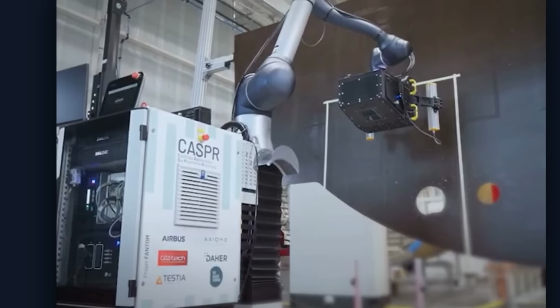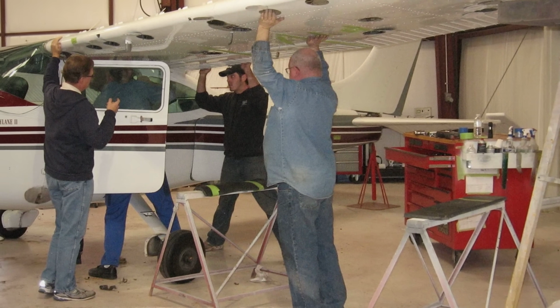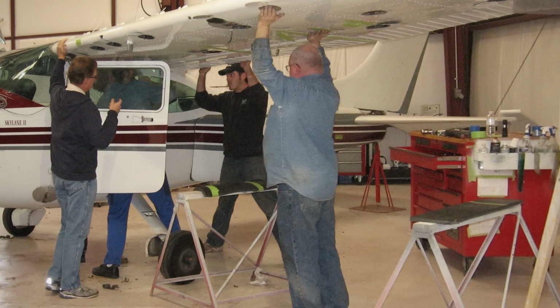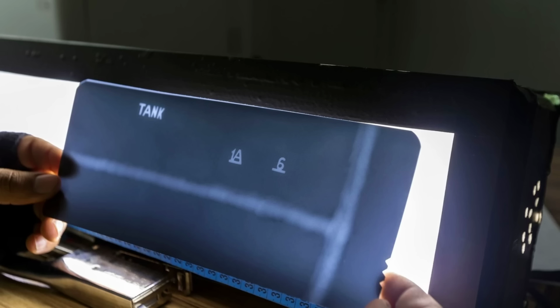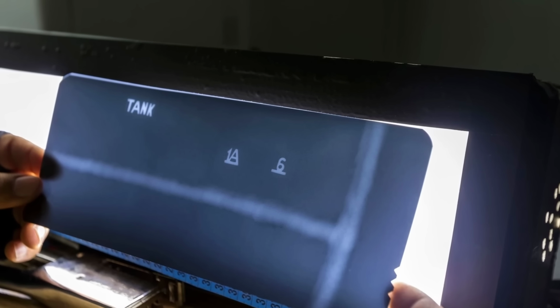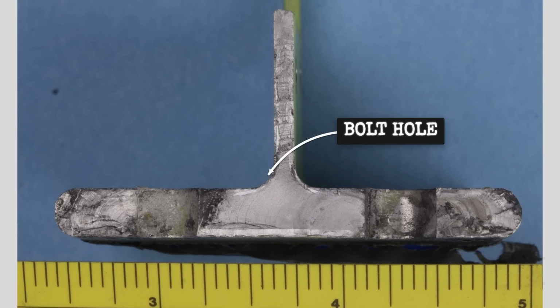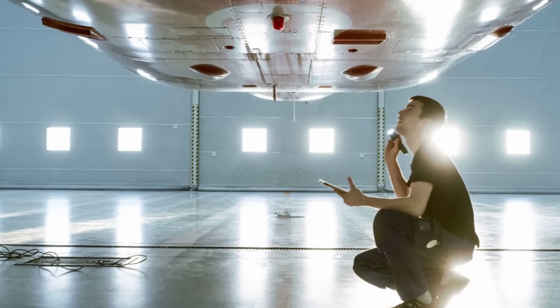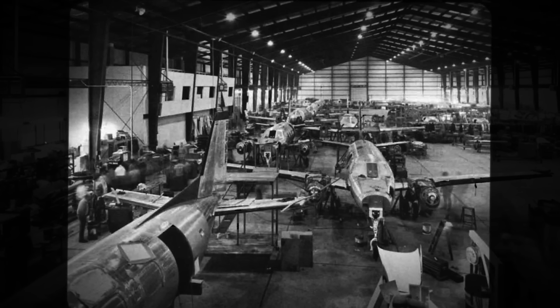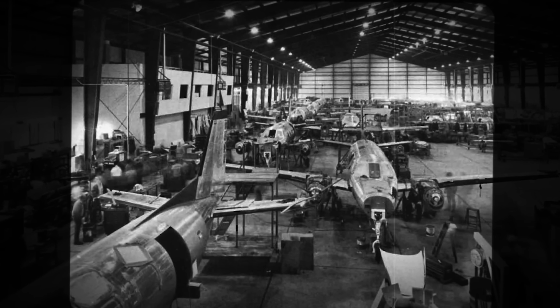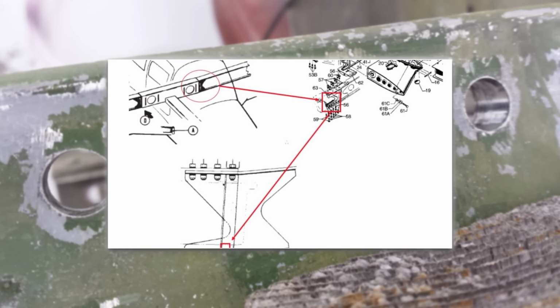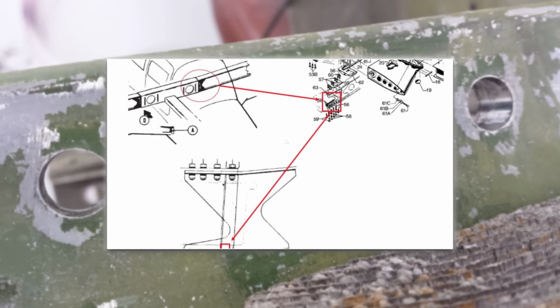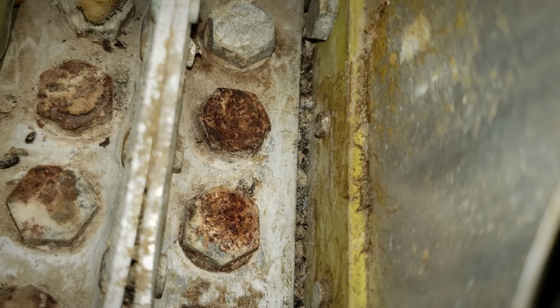The only way to know if you are safe is to pull the bolts and use high-frequency eddy current testing, or, better yet, radiography. A good X-ray does not just show cracks. It reveals crescent-shaped voids where corrosion has eaten away the metal from the inside out. It takes a certified tech and a patient owner, but it is the only way to catch a killer before it goes to work. Piper's own investigation found that cold bending during factory assembly left residual stresses right at the bolt holes, making them even more vulnerable. If those holes breathe, the wing will too.